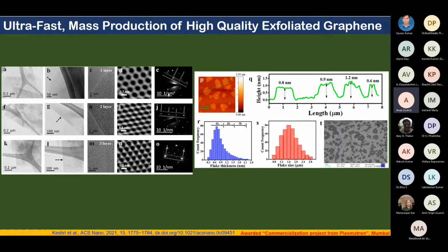And in the SADP pattern, the single layer has higher intensity in the two middle peaks, but the multiple layers, that is the two layer and three layer, have higher intensity at both corners of the planes. So this visual observation reflects that it has single layer, bilayer and trilayer. But we are not sure at this point how much percentage is single layer, how much is two layer and three layer.